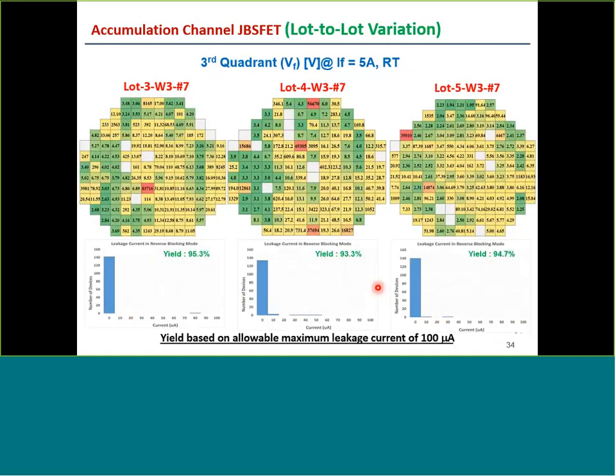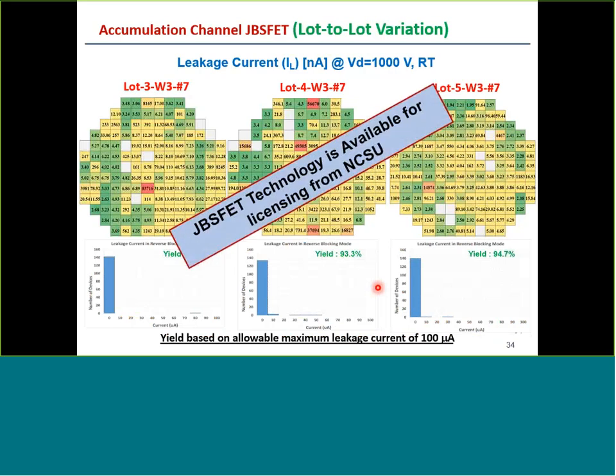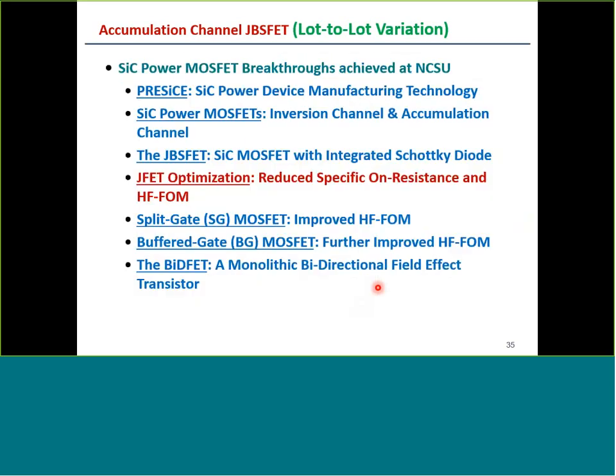The other important thing to note is that the leakage current of the JBS-FET is very good in spite of integrating the Schottky contact. This is by a combination of good design of the JBS contact area as well as the process used to make the chip. And the leakage currents for these devices are also in the nanoamp range, well below the 100 microamps. So this technology has been qualified, and if there is any interest in licensing, you can contact me at NCSU.